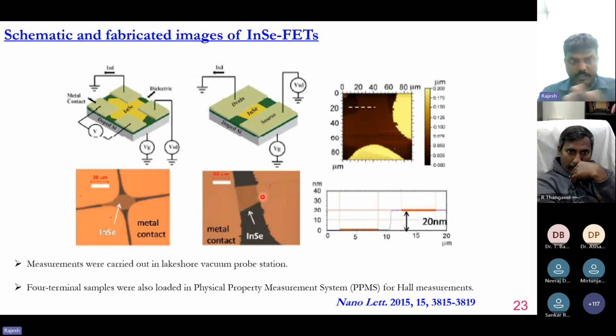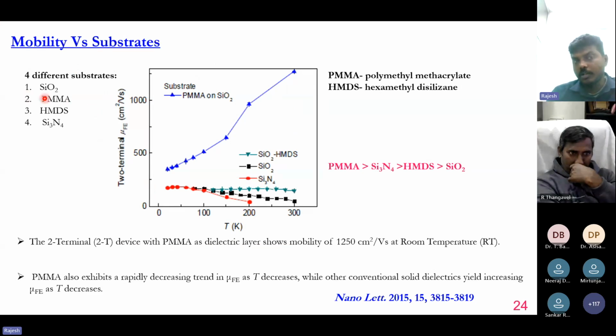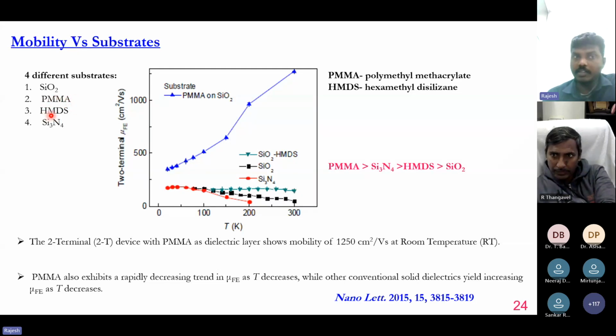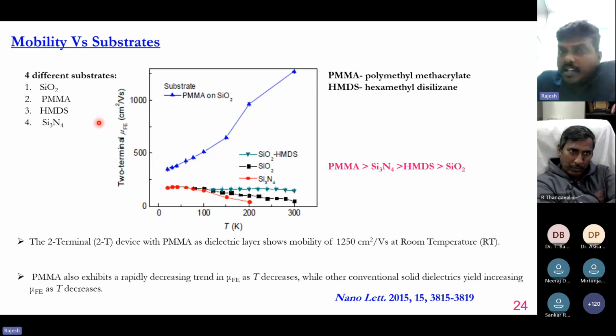Again, as I said previously, we fabricate devices with the help of exfoliation and the shadow mask technique. Here we used 4 kinds of substrate. One is a bare silicon substrate. On another substrate, we coated a polymer called polymethyl methacrylate. Then we coated hexamethyldisilazane on another substrate, and we used a silicon nitride substrate. On these 4 different substrates, we try to extract the intrinsic electron mobility of our pure indium selenide, and we clearly observe the polymer-coated silicon substrate showing a very high intrinsic electron mobility compared to the other 3 substrates.